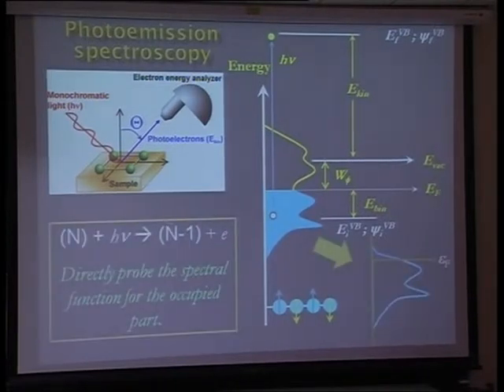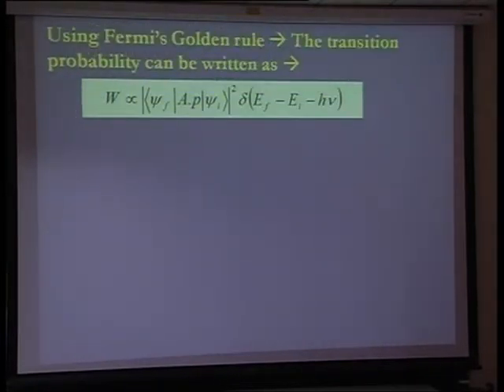So which represents the occupied part of the electronic structure. The strength of this technique is that you directly probe the electronic structure or spectral function of a system. Now, as I said earlier, since it's a quantum mechanical transition, you have an initial state and a final state, so the photoemission cross section of course depends on this transition probability, which is like a dipole kind of thing.